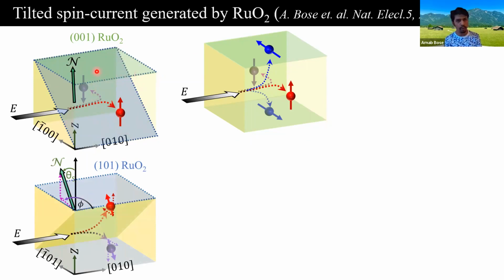Now, by rotating this with theta s along the z-axis, we can get the 101 plane here, and then this shaded area shows the 001 plane. So when we do the coordinate rotation, we also do the rotation of the spins. So naturally, in this plane, when we run current along the 0, 1, 0 axis, we naturally get a tilted spin current. This tilted spin current is the one that we want to experimentally detect.